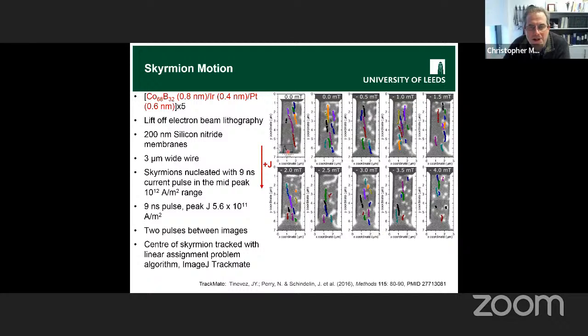And you can also see that it's not very reproducible. All of these skyrmions follow different tracks. Some of them move much further than others. So what's going on is quite disordered, and we're going to have to average over quite a lot of measurements to understand what's going on.